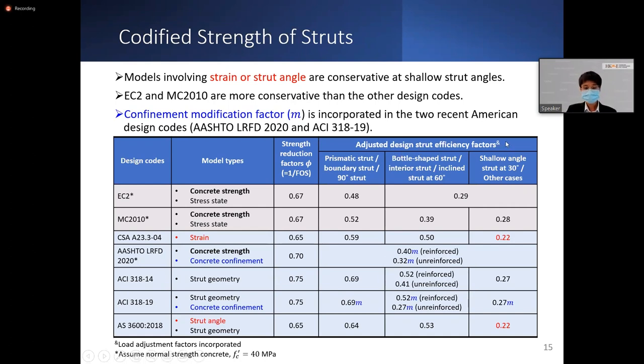You can see that in general, the strut efficiency factor decreases with increasing stress disturbance from left to right, such as from the 90 degree angle strut to the shallow angle strut at 30 degrees. However, for the Canadian standard and the Australian standard, which depend on the strut angle and also the strength, the design strut efficiency factor is rather small here, like 0.22 for the shallow angle strut at around 30 degrees. So they are rather conservative compared to the others.